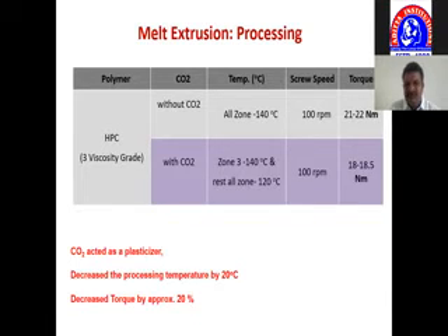So if you are using the same process, hot melt extrusion for extruding HPC, hydroxypropyl cellulose, and drug, we need to go for a temperature of around 140 degrees centigrade without carbon dioxide. The moment we add carbon dioxide, we are able to run a process 20 degrees lower than the actual process requirements. So we could run the process at 120 degrees centigrade. So what does this indicate? That carbon dioxide now acts as a plasticizer and thereby helps to reduce the processing conditions by 20 degrees Celsius.